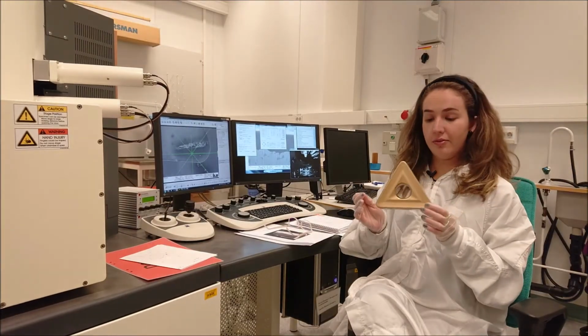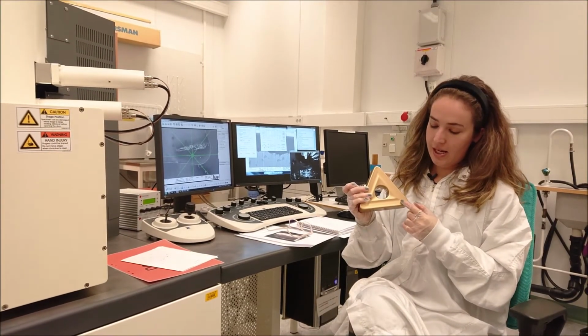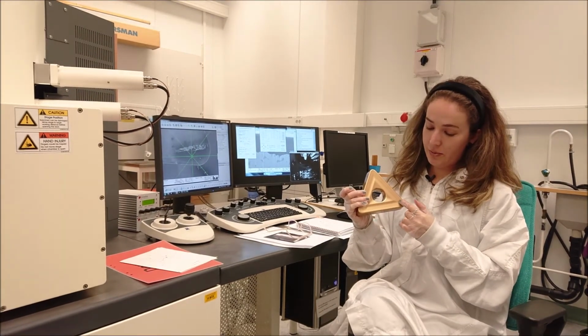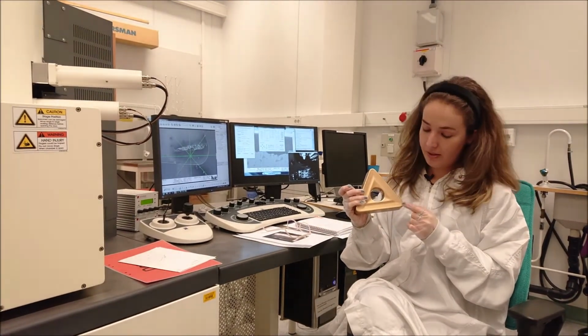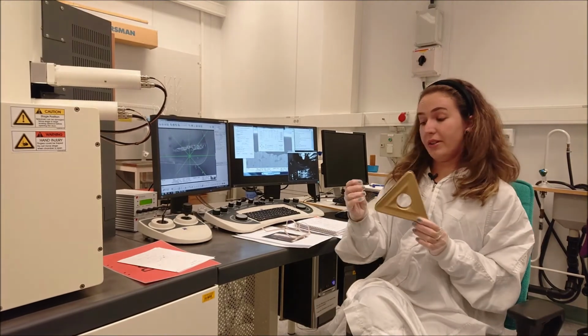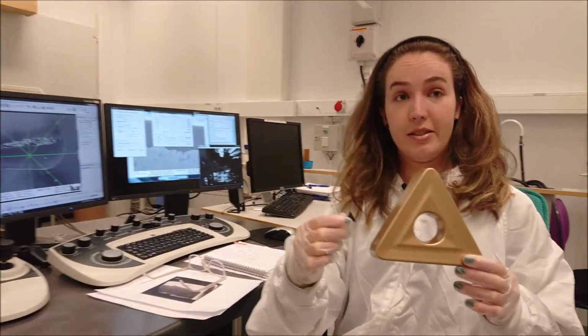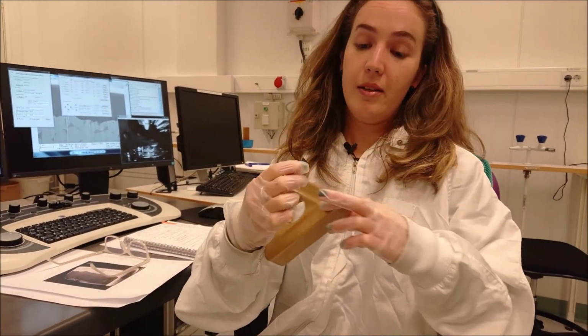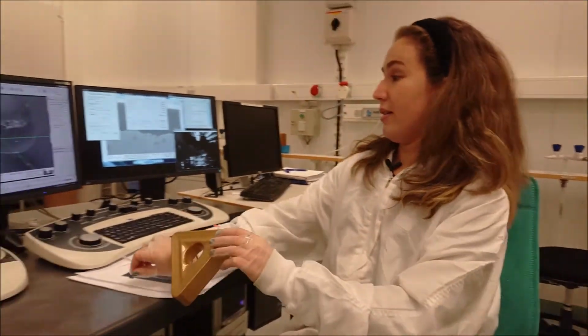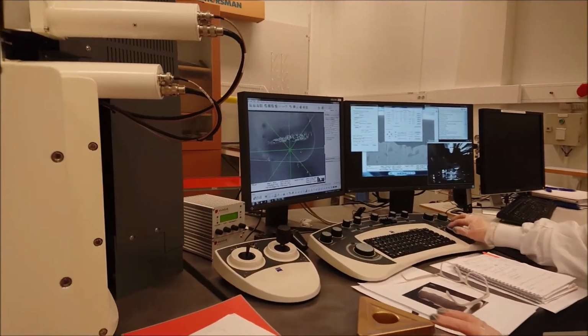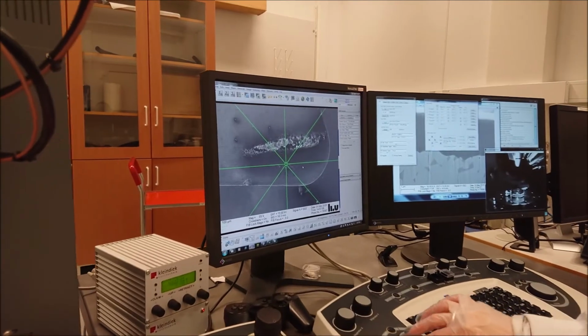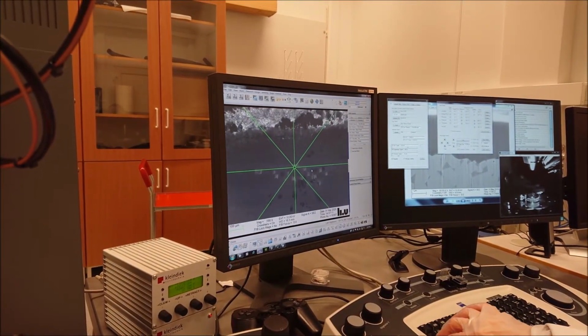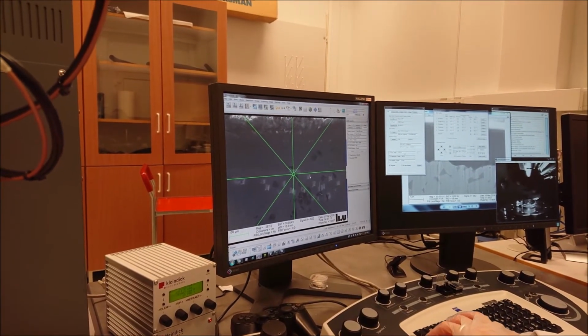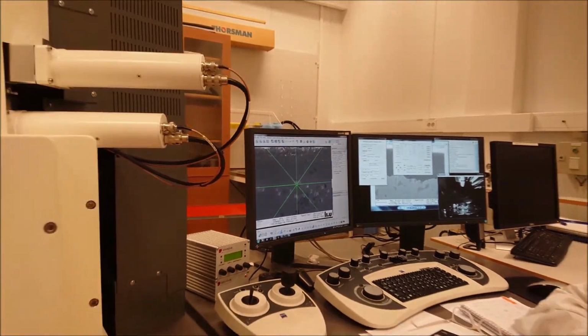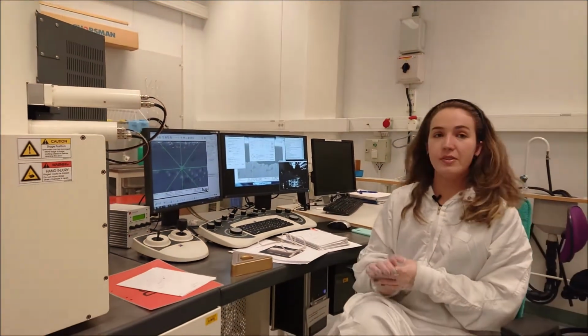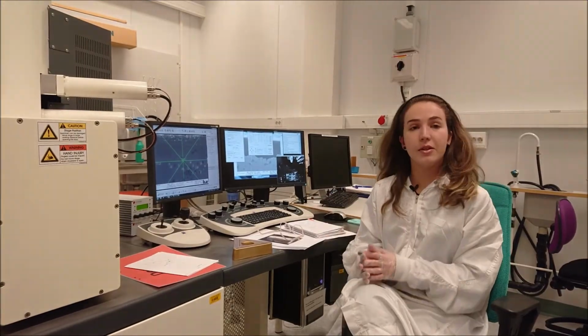Here we have a model of a cutting tool. In this project, I want to analyze the crater region that is on the edge. But in a real sample that looks like this, it's very, very small. It's here. So we need the FIB to see a very, very small area to get a lamella in the middle of the crater region. Without the FIB, I would not be able to investigate the wear in this area.